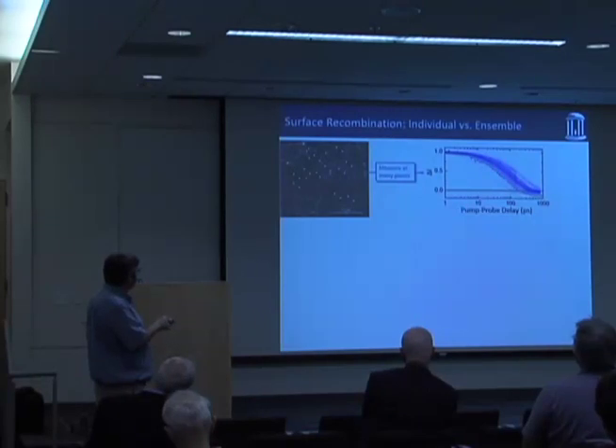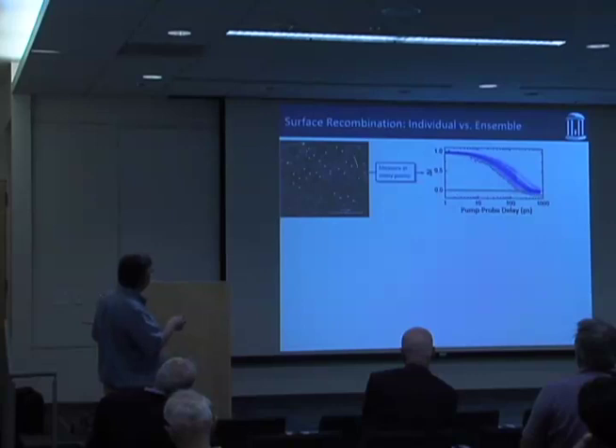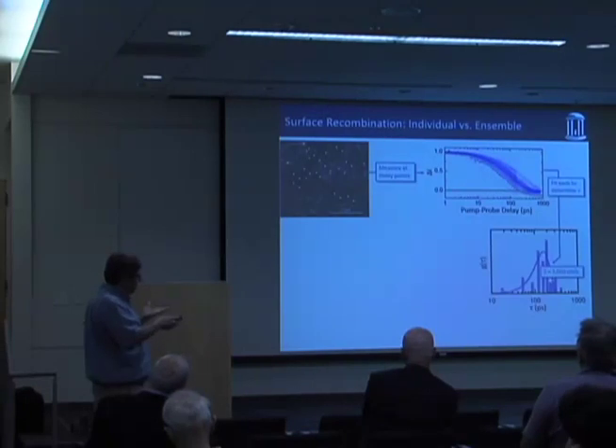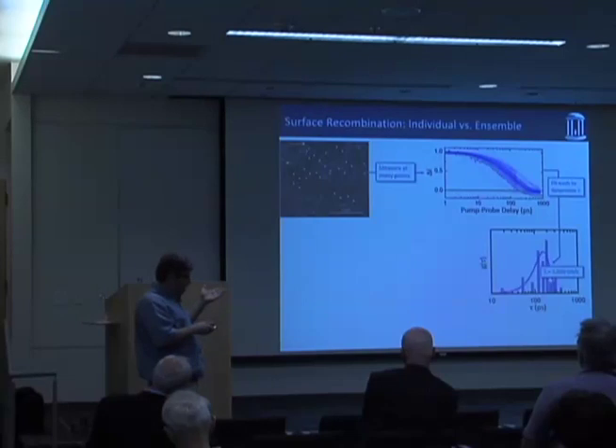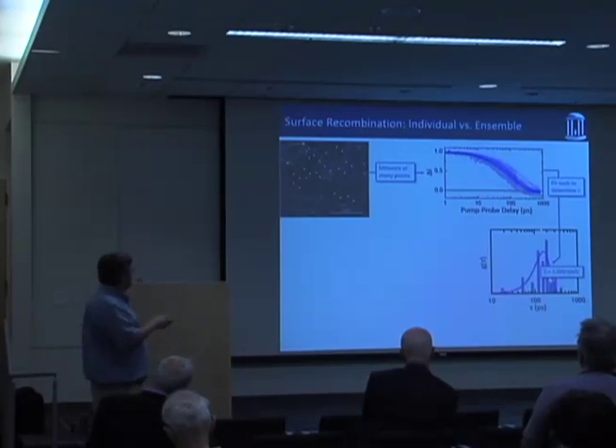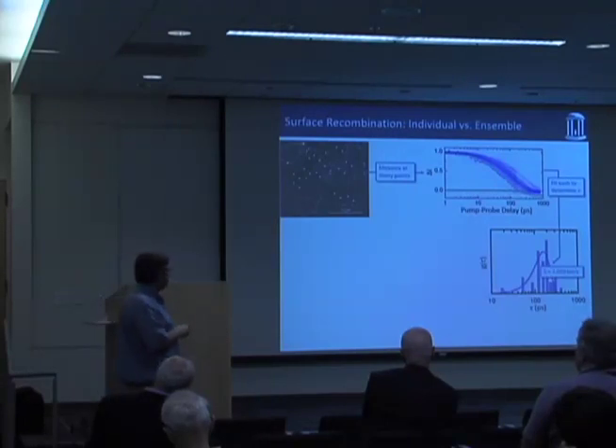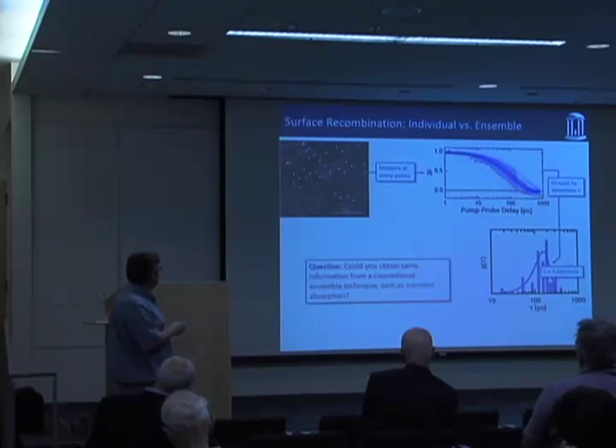They're plotted on a log scale here, but essentially they look exactly the same as the ones I showed you earlier. The first thing you see is that there's a wide distribution of decay kinetics here, which isn't necessarily all that surprising, given the heterogeneity in the sample. And we thought, well, we could take that equation, fit them to the expression I had on the previous slide, pull out a series of lifetimes, and get a distribution of lifetimes, and that's what's given down here. There's an average surface recombination velocity of about 7,000 centimeters per second. And so we felt pretty good about ourselves, and then we thought, well, we can check this because we're not 100% sure that we're right. We could actually do the transient absorption experiment, which is the ensemble measurement. And the question is, could you obtain the same information with the conventional technique?